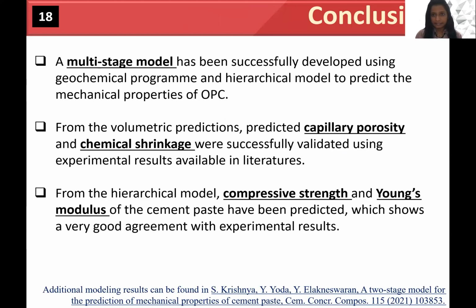And finally, these are the conclusions drawn from this proposed work. A multi-stage model has been successfully developed using a geochemical program and a hierarchical model to predict the mechanical properties of OPC. From the volumetric predictions, the predicted capillary porosity and chemical shrinkage were successfully validated using the experimental results available in the literature. From this hierarchical model, the compressive strength and Young's modulus of cement paste have been predicted, which shows a very good agreement with experimental results.